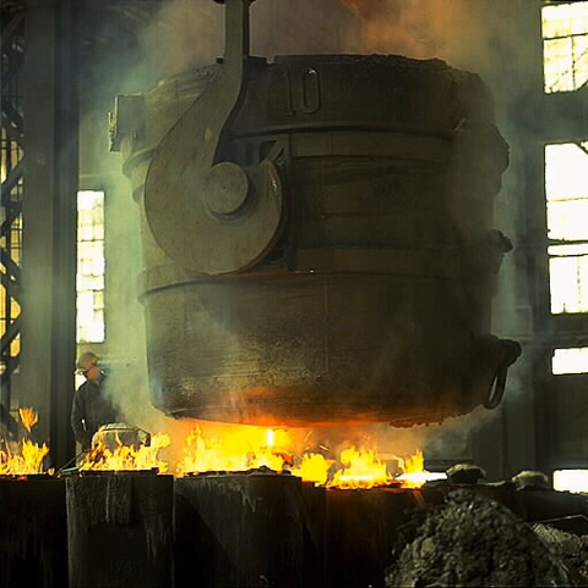These eutectic carbides are much too large to provide the benefit of what is called precipitation hardening, as in some steels, where much smaller cementite precipitates might inhibit plastic deformation by impeding the movement of dislocations through the pure iron ferrite matrix. Rather, they increase the bulk hardness of the cast iron simply by virtue of their own very high hardness and their substantial volume fraction, such that the bulk hardness can be approximated by a rule of mixtures. In any case, they offer hardness at the expense of toughness.